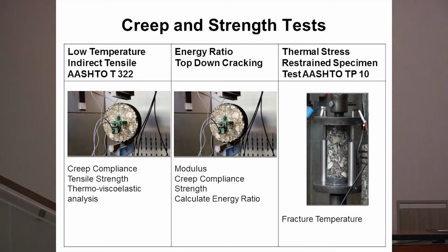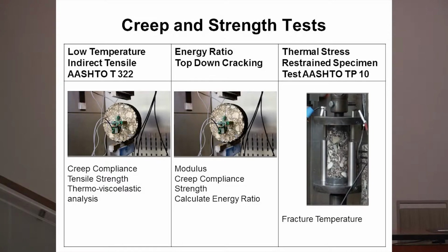The low temperature indirect tensile test and the energy ratio test both use the indirect tensile geometry with instrumentation applied to it. What you measure for low temperatures are creep compliance and tensile strength, and you put that data into a thermoviscoelastic analysis to predict cracking. Quite time consuming to do the low temperature indirect tensile test. The energy ratio test is the only one that I know of that is specifically related to top-down cracking.